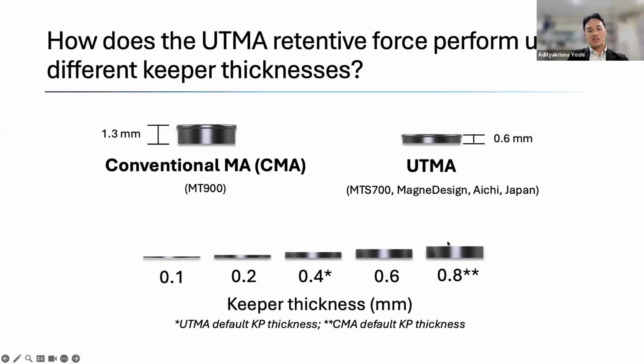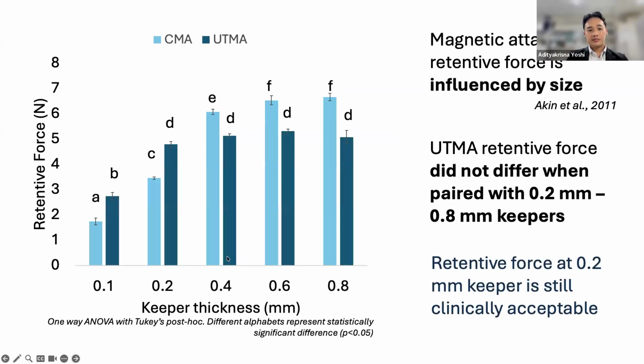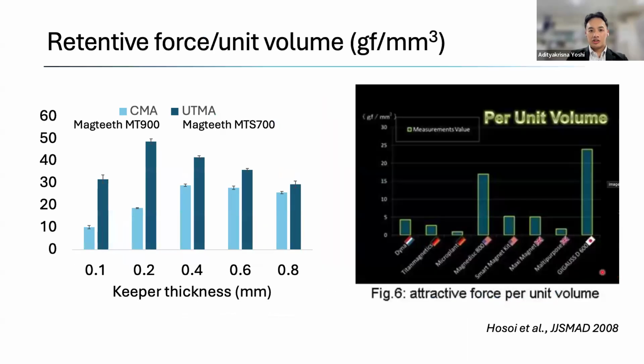So from that study by Tanaka et al., we wondered, if the thickness of the ultra-thin keeper is reduced, how about the retentive force? Could it still provide an adequate retentive force or not? So we performed this experiment further, and we figured out that with the ultra-thin magnetic attachment system, even when reducing the keeper thickness to 0.2 millimeters, the retentive force did not reduce significantly from 0.8 millimeter down to 0.2 millimeter keeper thickness. So we concluded that even reducing to a 0.2 millimeter keeper, it can still provide clinically acceptable retentive force.